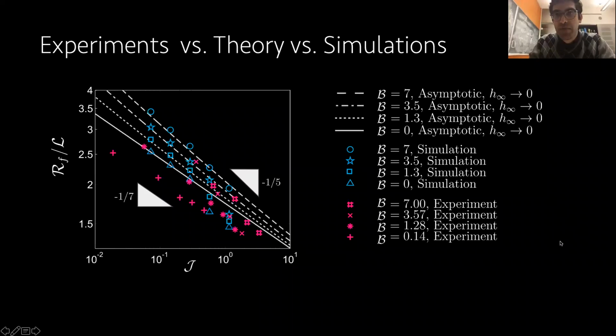There are multiple parameters, like the exact value of the surface tension of Carbopol, that we are not sure about. When the J number goes high, meaning the yield stresses are high, your deposition history becomes very important. The way you deposit the droplet can be the reason for some of the discrepancies, the mess that you see here, and some other reasons, including the effect of elasticity, which is not in any of our models. Okay, so this sums up the spreading part that I wanted to say.